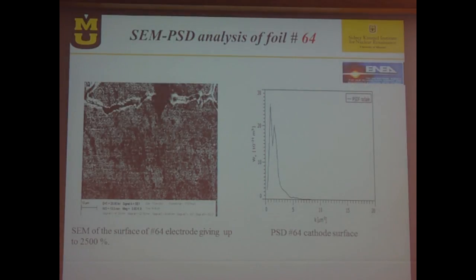We came to the conclusion that the x-axis, the y-axis is the amplitude: the higher the amplitude, the higher the probability for excess heat. And the fact that we saw these 2 peaks, you will see them in many other surfaces that we have analyzed. It's a good indication for getting higher reproducibility and getting excess heat.